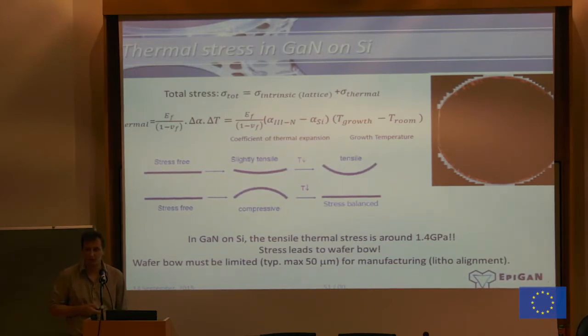So we have done hetero-epitaxy. I have shown you the problem you have with strain that you build up when you grow on top. If you grow on silicon, you have a second issue, which is the thermal mismatch, which is nothing different than the fact that if you grow these materials at very high temperature, after the growth, you have to cool down the materials, and the thermal expansion coefficients of silicon and gallium nitride are very different. So if you cool down, in this step here, you create a very large tensile stress. So what we need to do during the epitaxy is build in, by designing our buffer layer stack, a significant amount of compressive stress, so that after we have grown this thing and cooled it down, in net, you have a flat wafer.